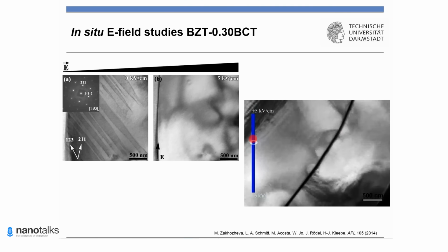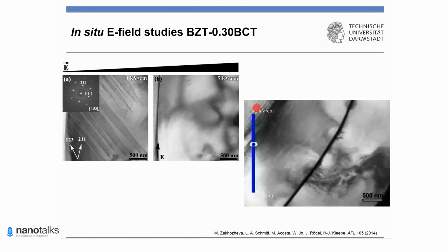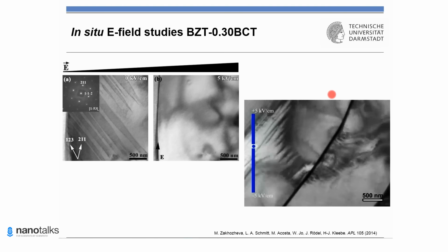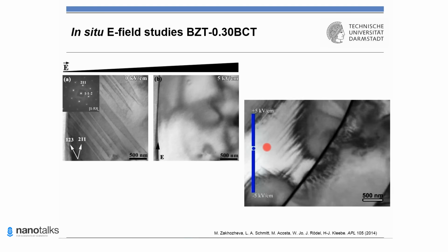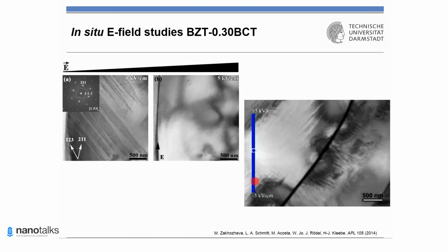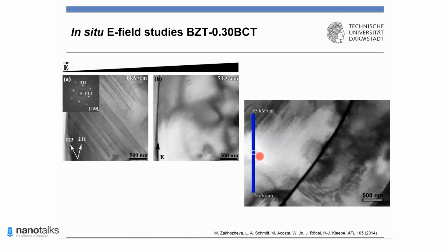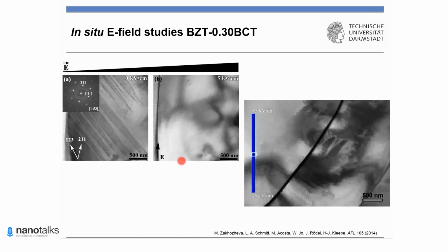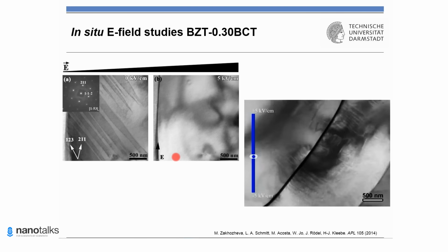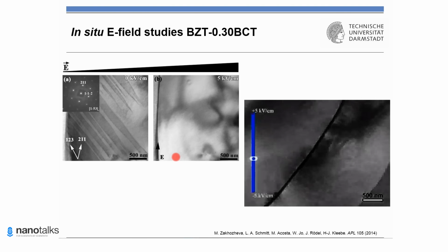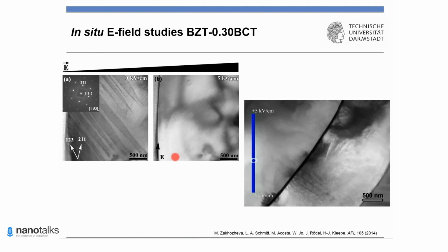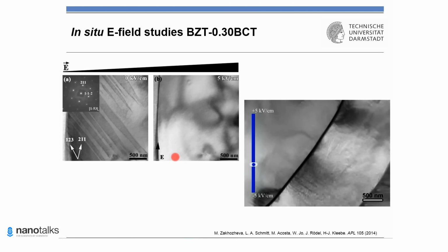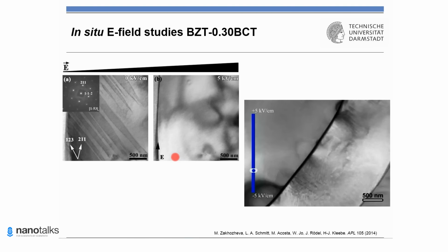Basically, with reducing electric field, we see that this single to multi-domain transformation occurs. So we have a completely reversible transformation in that case. And at zero field, we have a multiple domain contrast again. Changing polarity leads to the same result in the other direction. So what did we have? We saw an electric field induced transformation from multi to single domain state, and this actually occurred at moderate poling fields. And this transformation is found to be reversible, since the multidomain contrast reappears on field removal.